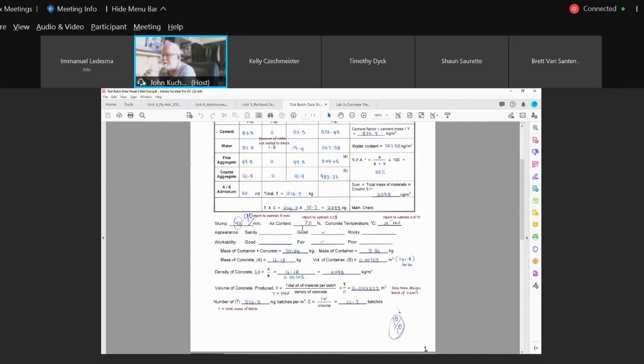Okay, PCL calls you out. They want a concrete test done on their pour that they're placing concrete. You go out there and sample the concrete in accordance with CSA standards. You bring it over to where you're going to make your cylinders and leave them for the first 24 hours, and away you go. So you take a temperature, you do a slump, an air test, a density, then you cast some cylinders.